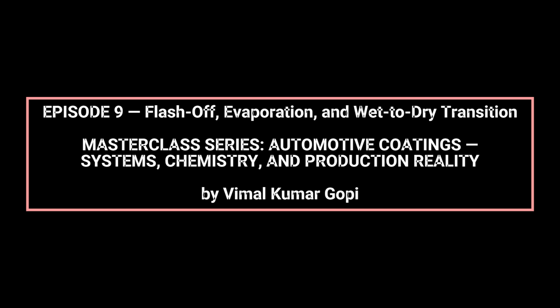In basecoats, flash-off is critical for metallic and effect pigment orientation. During the wet phase, flakes align under gravity, surface tension gradients, and shear relaxation. If solvent evaporation is too rapid, viscosity increases before flakes can orient properly, resulting in mottling, patchiness, and poor flop. If evaporation is too slow, flake movement continues too long, increasing flooding, striping, and color non-uniformity across complex vehicle geometries.